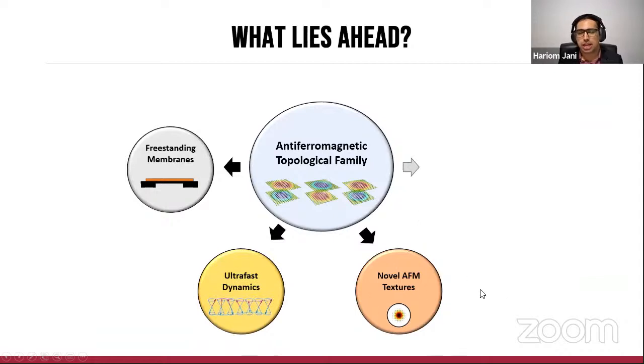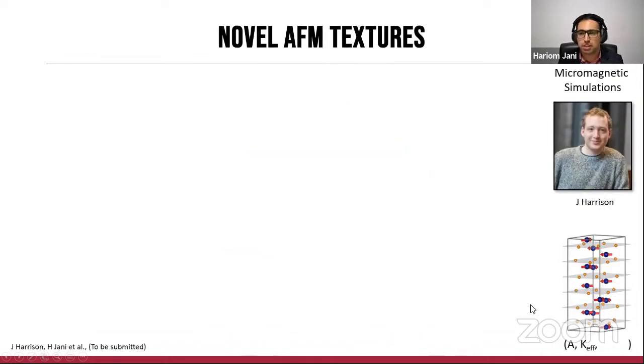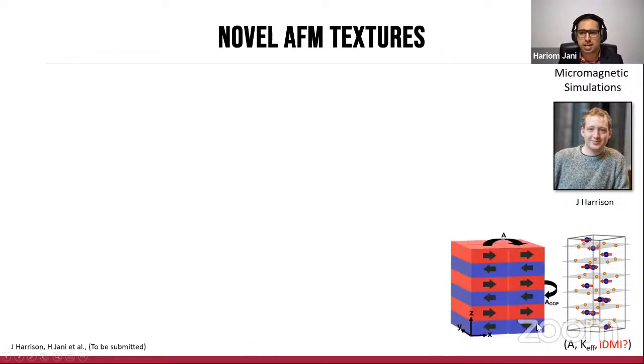Now, another investigation I would like to share is, can we observe novel antiferromagnetic textures beyond the Kibble-Zurek regime in this material system? And that is a work done by my colleague, Jack. This was done now using micromagnetic simulations, not atomistic, because we wanted to add a new term here, which is a symmetry breaking interfacial Dzyaloshinskii-Moriya interaction. This is some work where we investigated if we start off with various layers of Fe2O3. Now, because it's a micromagnetic approximation, there is a slight inaccuracy here, but this is still good enough for us to actually start the investigation where individual layers are ferromagnetically oriented and adjacent layers are antiferromagnetically oriented. And this allows us to effectively create the layered structure of Fe2O3 and allows us to investigate what would happen if an IDMI is hypothetically added to the structure.